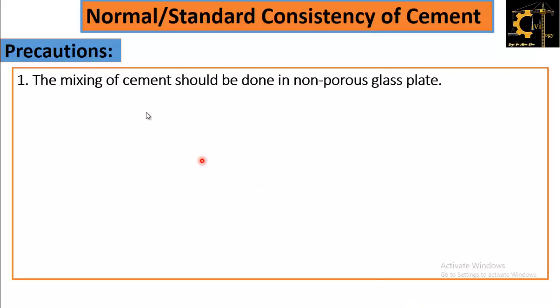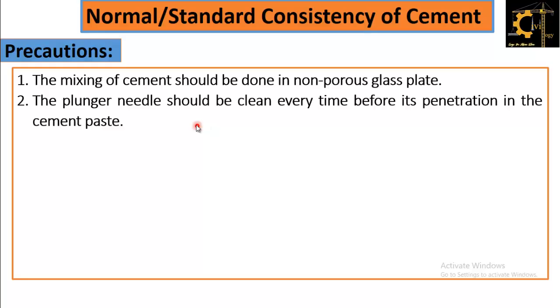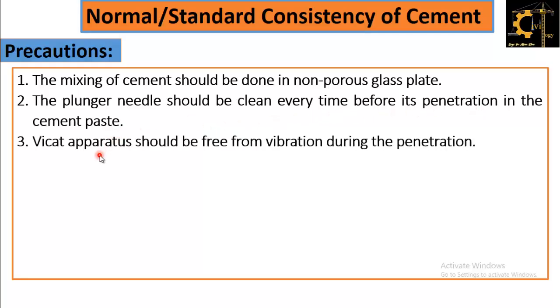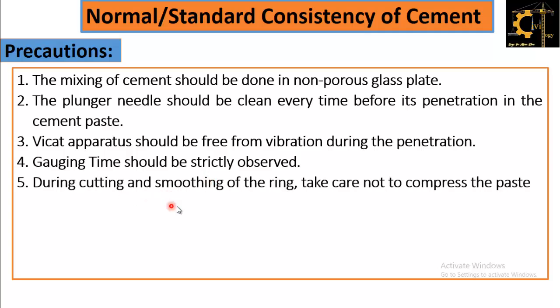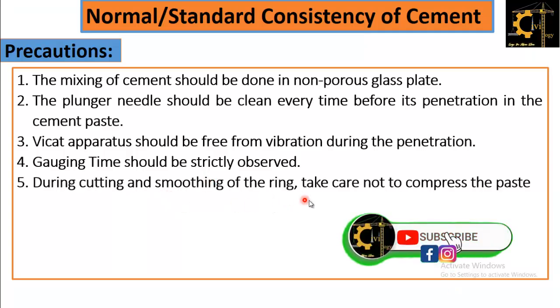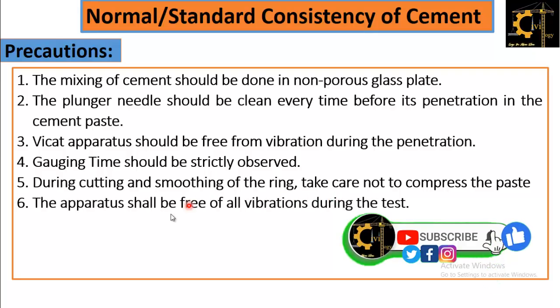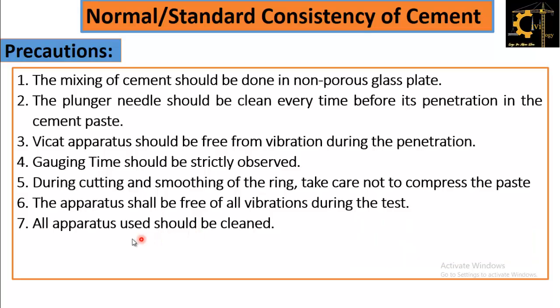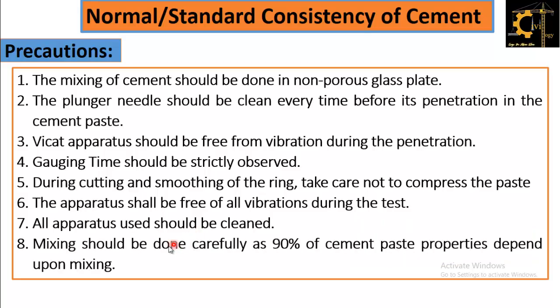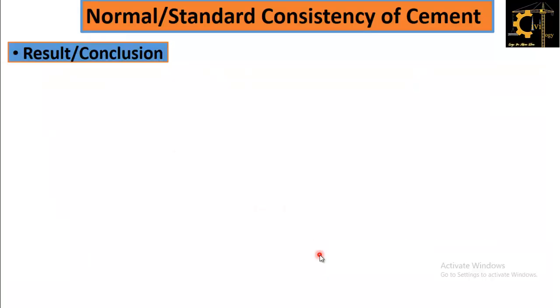Precautions: the mixing of cement should be done on a non-porous glass plate. The plunger needle should be cleaned every time before its penetration in the cement paste. The Vicat apparatus should be free from vibration during the penetration. Gauging time should be strictly observed. During cutting and smoothing of the ring or mold, take care not to compress the paste. The apparatus shall be free of all vibrations during the test. All apparatus used should be cleaned. Mixing should be done carefully, as 90% of cement paste properties depend upon mixing.